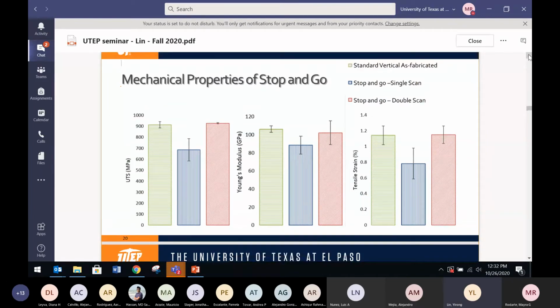One of the problems is when you embed a sensor into metal components, or into any component, there's always a trade-off, right? It's really hard to get the best of both worlds. Once you embed a sensor, what are you losing? You're losing mechanical properties. So this green line is a fabrication without interruption, and the blue is stop and go: you stop the fabrication, embed a sensor, and then finish your fabrication. What do you see here? You are lowering its ultimate tensile strength, you're lowering its Young's modulus, and also its tensile strain. Because of stop and go, it cools everything down and really halts the grain growth. So your material property at the interface is always bad, right?